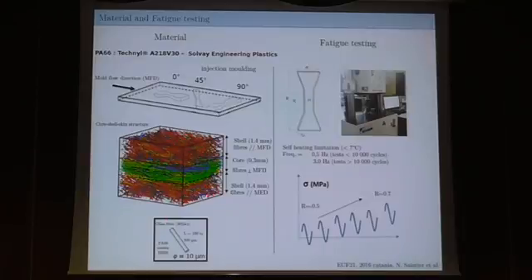With a core shell microstructure, you will have globally, for example, for the zero angle specimen, fibers along the mold flow direction, but in the core of the material, we'll have a small layer, 300 microns of 90-degree material. So it's globally 0-degree angle, but you always have some misorientation in the center of the specimens. Glass fibers, it's 10-micron glass fibers with lengths between 100 and 800 microns, and we did some fatigue testings with classical uniaxial loadings with loading ratio between -0.5 and 0.7.